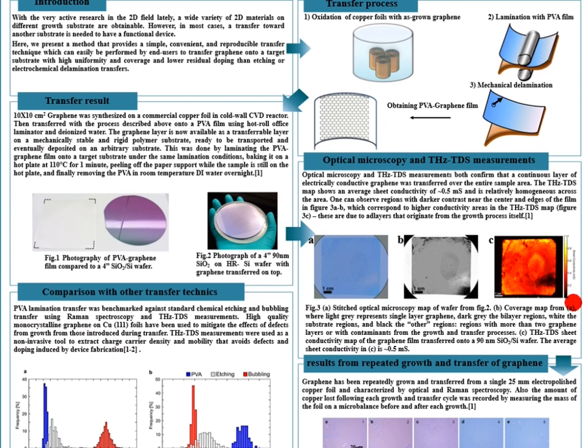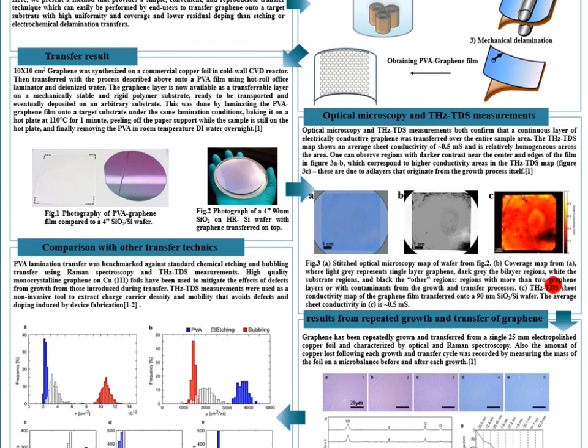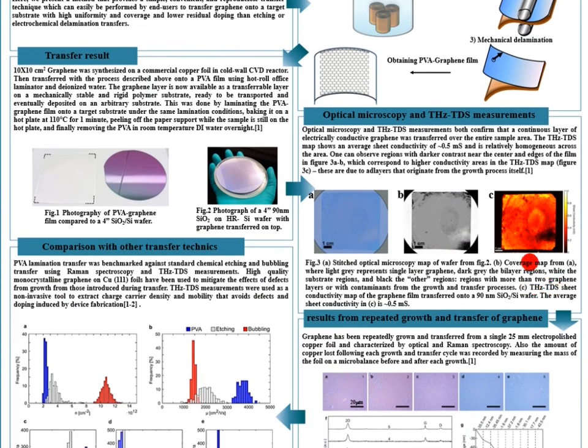Optical microscopy and terahertz TDS measurements both confirm that a continuous layer of electrically conductive graphene was transferred over the entire sample area. The terahertz TDS map shows an average sheet conductivity of approximately 0.5 millisiemens and is relatively homogeneous across the area.